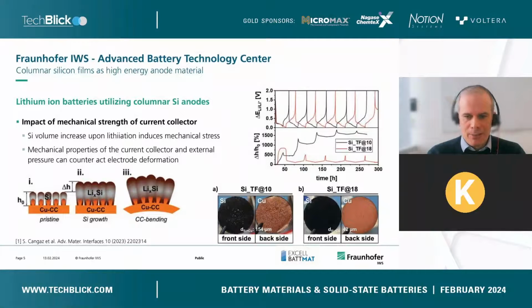You see two examples of silicon films being used in coin cells, where in one cell we used a current collector with 10 micrometer thickness, the other of 18 micrometer thickness. This is just an example to show that the mechanical strength of the foil can avoid the wrinkling and the deformation we see for the 10 micrometer foil. Just when we go to a more stable and a bit thicker current collector, we can avoid this, and we can observe the stabilization and